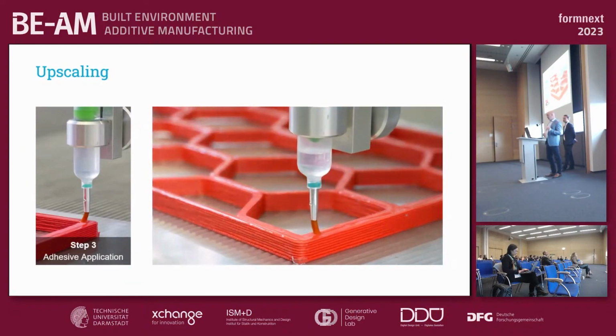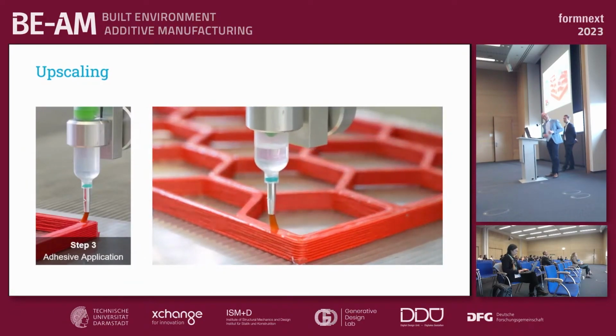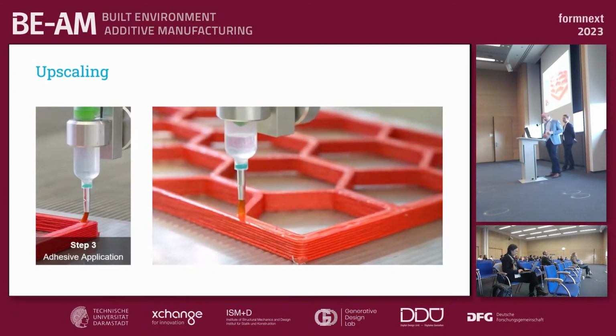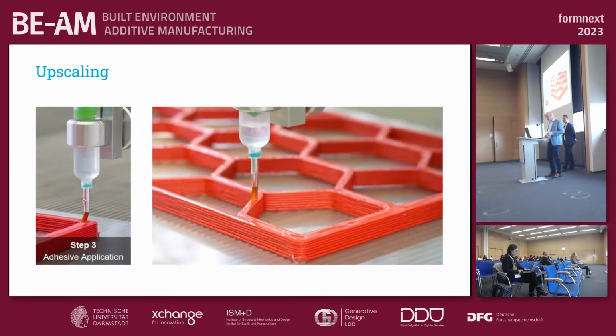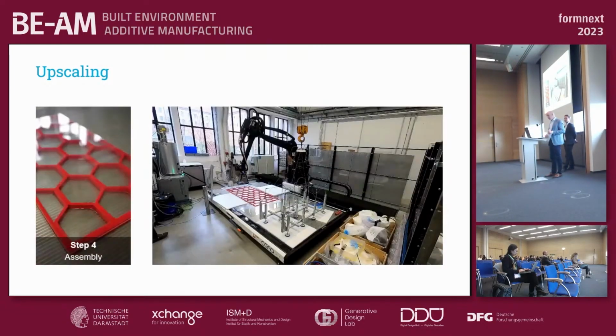So until the point that you apply the light, you can still maneuver and you can still take your time to apply the adhesive. Another thing is that this adhesive is normally very thin, less than 1 millimeter, so you don't have that much capacity to compensate for tolerances. That's why we really want to mill it down to have a smooth surface for the gluing. And later Daniel will show a bit more about hot melt adhesives, which are a bit more tolerant in terms of sizing.